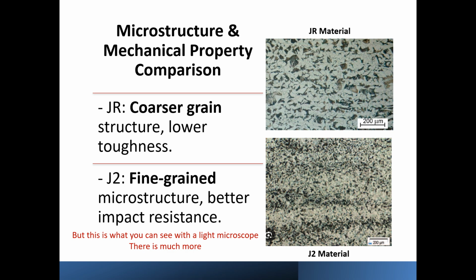And how that material looks under the microscope, you can see in the top image, the grains are much larger in comparison to the bottom image. And that grain size difference, just that grain size difference, makes a huge difference to the mechanical properties. But this is just what you can see with a light microscope. And there's much more than this.